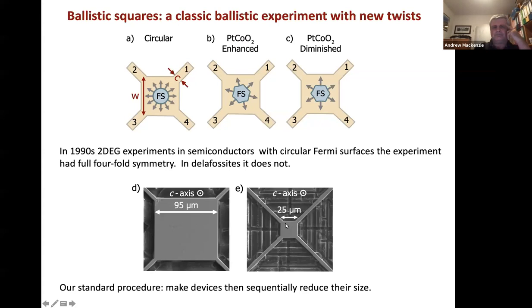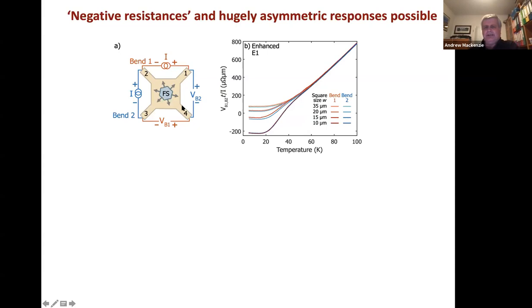So what do you see? Well, in the enhanced orientation, you see a very pronounced effect, but it's an effect which is similar to what you would have seen with a circular Fermi surface. So you're trying to do a bend resistance measurement. So you drive current in these two contacts. You're trying to bend it round the corner. In the ohmic regime, in this square geometry, you will get a certain resistance appearing through the voltages 3 and 4 when you do that. And that resistance will be the same whether you run the current this way or this way, right? And it's exactly the same. And so whatever you do, you just get the ohmic resistance up at 100 Kelvin.